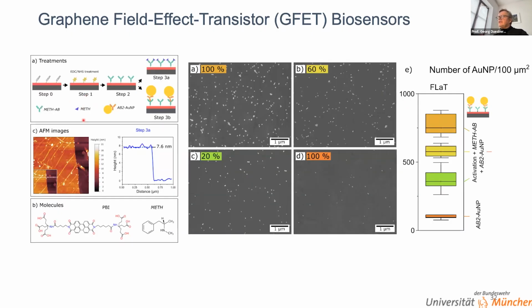As shown here, we use these coupling reagents. These are the molecules we have. We have the carboxylic functions, and then we use these EDC NHS treatments to attach antibodies onto this functional layer on graphene. And what is shown here on the right side in the SEM images is that we can control nicely how many antibodies we attach to the surface.